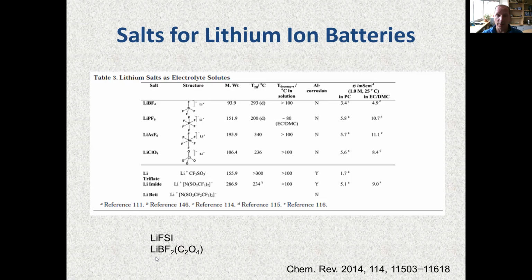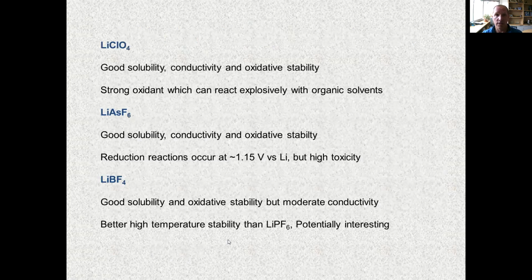And then another salt that's received a significant amount of interest is lithium difluorooxalatoborate. And so we'll go over each of these salts quickly. So first off, lithium perchlorate. Lithium perchlorate has very good solubility, good conductivity, and reasonably decent oxidative stability. However, lithium perchlorate itself is a strong oxidant which can react explosively with organic solvents.